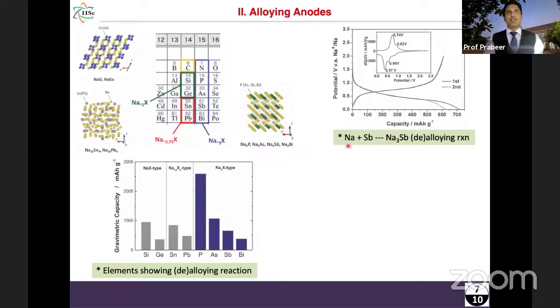Basically, sodium reacts with Sb to form NaSb, then Na2Sb, then finally Na3Sb. So basically, 3 sodium can react to form Na3Sb, and as a result of the 3 sodium reaction, it can give rise to very high capacity, close to around 600 milliamp per gram with the voltage around 0.7 volt. So here at a low voltage, we are getting very good capacity with good cycling stability. So this is one potential anode material for sodium battery.